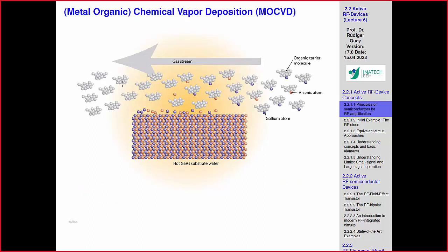It's essentially you put a gas stream with a precursor. So there's a lot of organic carriers, and what you do is you create, it's like an airplane flying and dropping something, not a bomb in this case, but gallium and arsenide in this case. And if you mix the gas proportion right, at the right temperature, there's always one gallium, one arsenic, one gallium, one arsenic. And we do it at high temperature. Why? Very simple, because then the movement of the carrier on the surface is still arranging to a very perfect crystal. So if they're landing, but they may have not gone to the right position, because of the temperature, they're still moving.